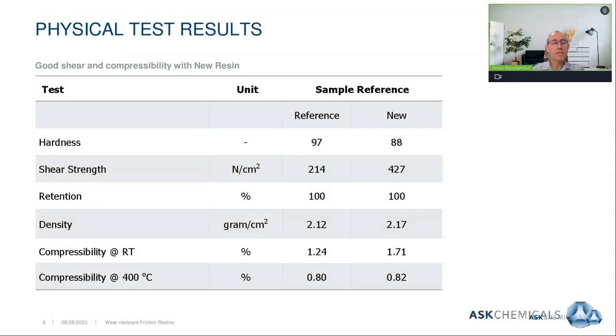Here we show the physical test results that we obtained of the older technology, what we call a reference here, compared to the new wear-resistant technology. You will see that in hardness as well as in compressibility, one can see a softer matrix from this modification that we have done. And it then interprets well into the shear strength, which is substantially better with the new technology. Density and retention is quite stable and comparable. And as I said, compressibility slightly improved at lower temperature as well. And I do point your attention to the significant improvement in shear strength as well.